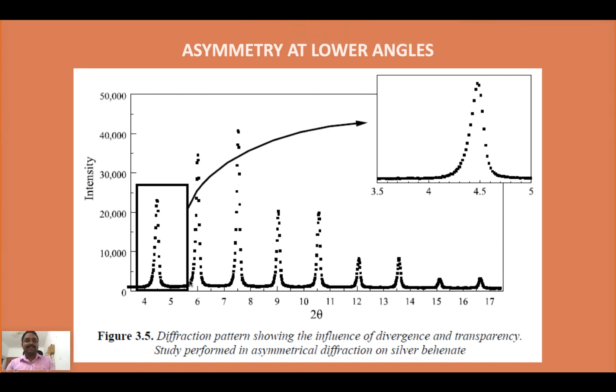below 2 theta 10 degrees. That is why I told you to restrict to 10 to 90. At higher angles this peak asymmetry will also arise, so the better approach is 10 to 80 or 70, which is enough for normal samples. If you specifically want the lower order peaks, go for less than 10 degrees.